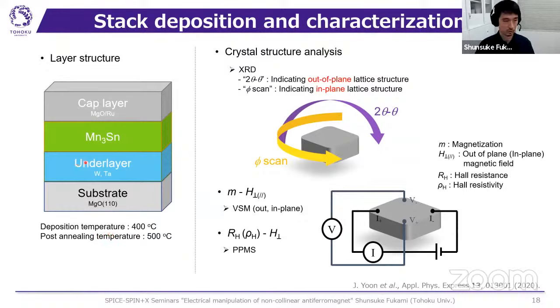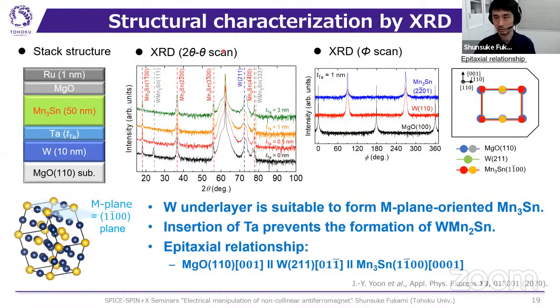When we deposit this film, we heat the stage to up to 400 degrees Celsius. After that, we also anneal the samples at high temperatures. To characterize the crystalline structures, we mainly use XRD, and we also use VSM and PPMS to evaluate the magnetic and magnetotransport properties. Let me show the structural characterization by XRD.